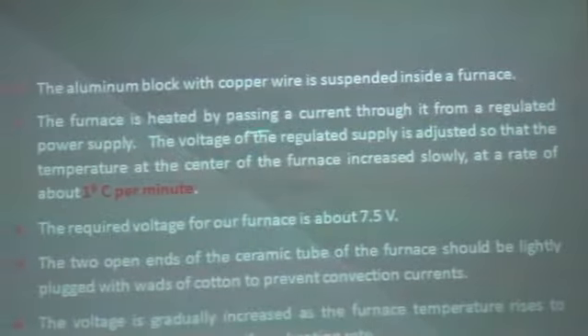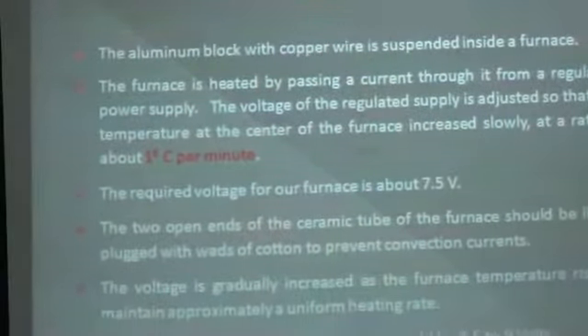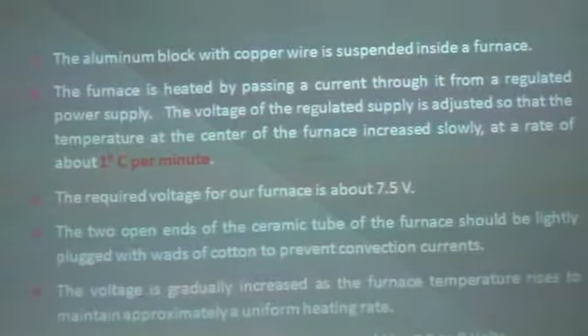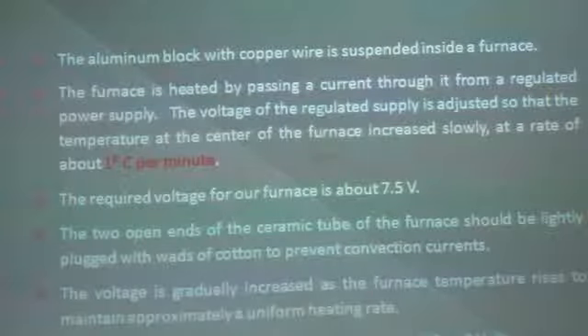Here in this case, the furnace is heated by passing a current through a regulated power supply. Again, similar to the previous experiment that we discussed yesterday in the afternoon, the voltage of the regulated power supply is adjusted in such a way that the temperature at the center of the furnace increases slowly at a rate of 1 degree centigrade. Even if you are in a hurry, you have to follow this, otherwise you will not end up with the right result. Suppose in the afternoon around 3 or 4:30 you are in a hurry to run home, and you increase the voltage to 12 volts. You will get the readings, but the readings will not give you the right result, and Professor Srinivasan will ask you to repeat the experiment next day.